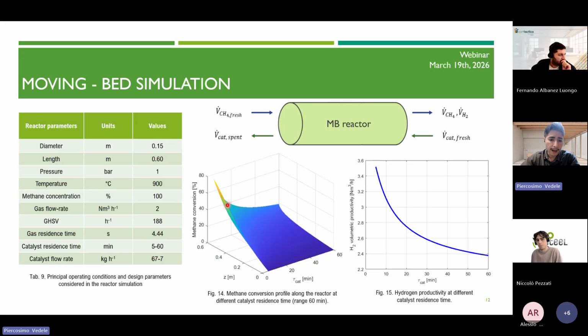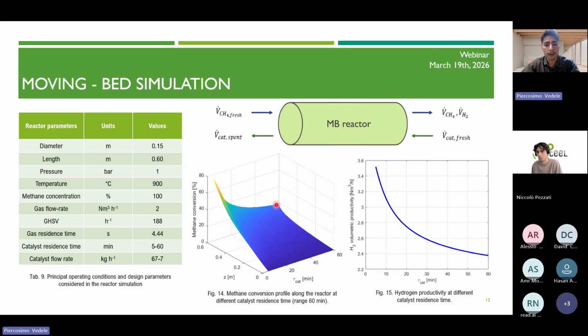Maybe here you can see this reasoning better. At low catalyst residence time, we have higher conversion, but of course this kind of reactor characterized by really low residence time is not so easy to manage. By increasing the catalyst residence time, we are also reducing the methane conversion, but we have a reactor which is easier to manage. Of course, this kind of technical study must be coupled with an economical study to evaluate the best trade-off from the point of view of the technical issues and the economical issues.